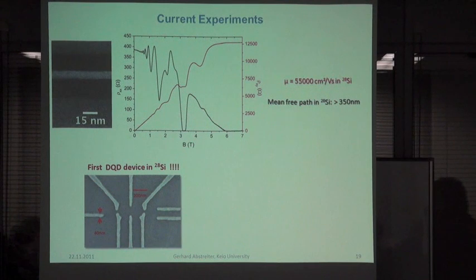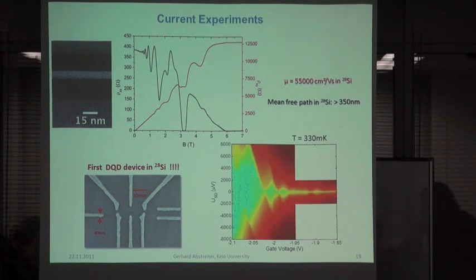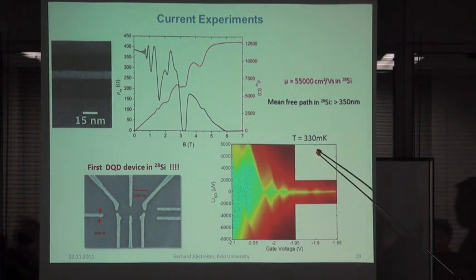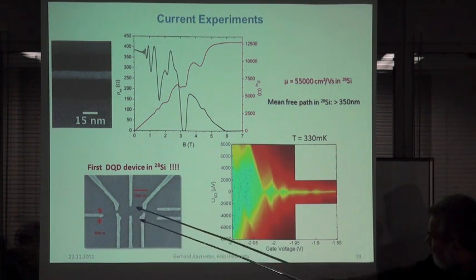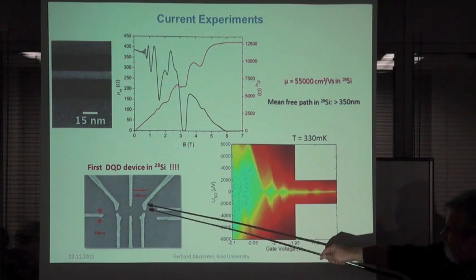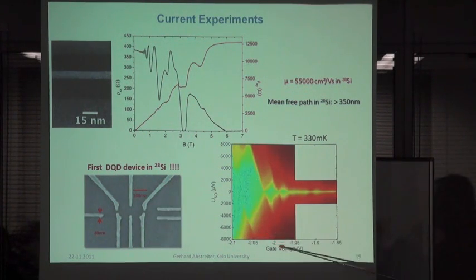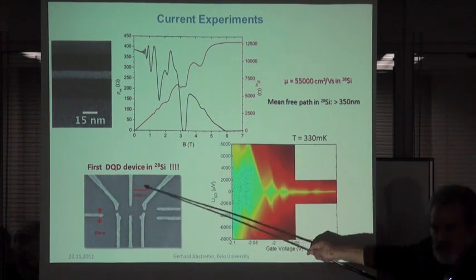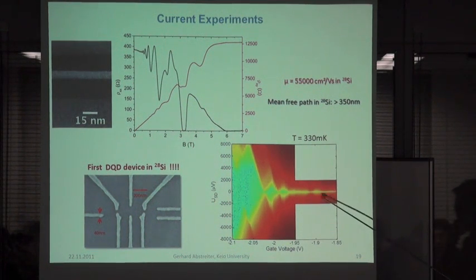We have made these devices, and in the moment they are in the cryostat. This was a pre-measurement at 330 millikelvin, gate voltage left and right here. So this is just measuring the charging with one gate voltage and source drain currents through here. And in the moment we have transferred this sample to the dilution fridge in Stefan Ludwig's lab in the Ludwig-Maximilians University in Munich. And there are very nice results already coming out now for this isotope clean material. And it looks very stable from the gating.